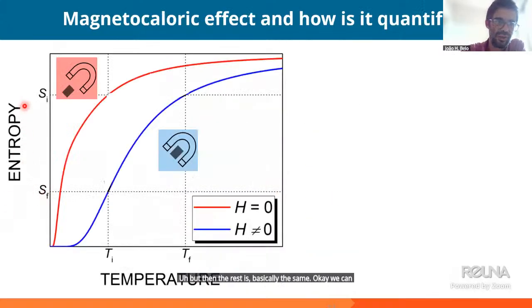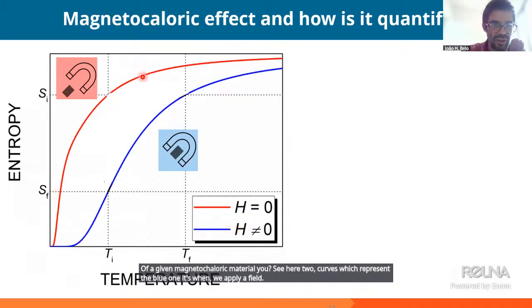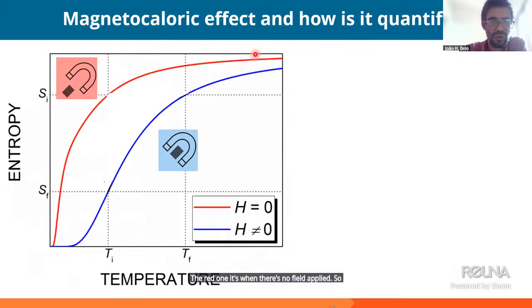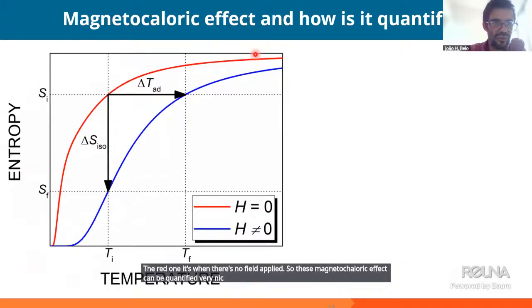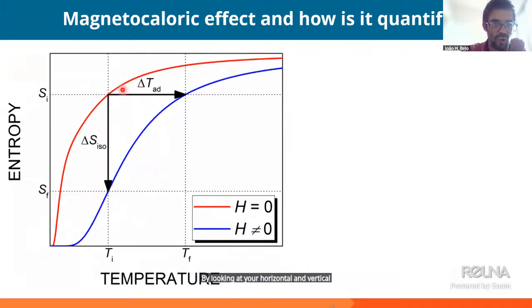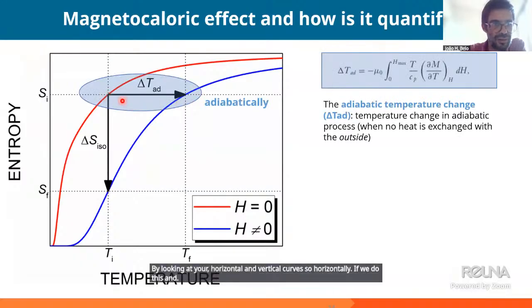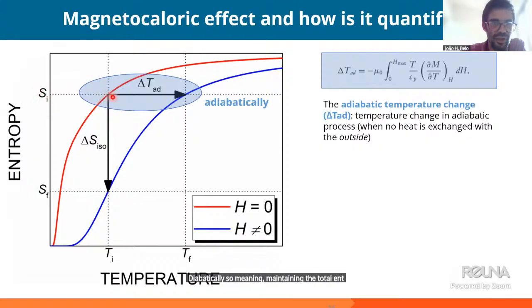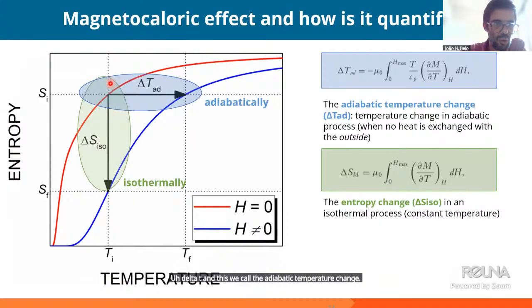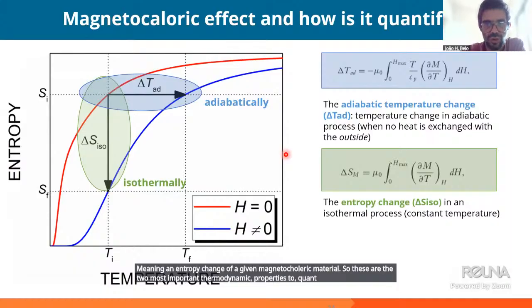Okay, we can also look at this in the entropy versus temperature curves of a given magnetocaloric material. You see here two curves, the blue one is when we apply a field. The red one is when there's no field applied. So this magnetocaloric effect can be quantified very nicely using these graphs by looking at the horizontal and vertical curves. So horizontally, if we do this adiabatically, meaning maintaining the total entropy of our system, we will have delta T, and this we call the adiabatic temperature change. If we go vertically at the same temperature, so isothermally, we will have a delta S, meaning an entropy change of a given magnetocaloric material.